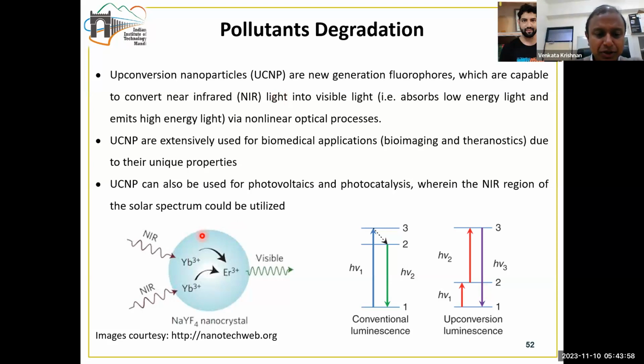When we look at this upconversion nanoparticle, it basically consists of sodium yttrium fluoride as a lattice. It's a nanocrystal type of lattice, and this lattice is doped with certain lanthanide cations such as ytterbium and erbium. One of these lanthanide cations acts as the sensitizer, and the other one plays an active role as the activator. And by tuning the identity of this lanthanide material, we can tune the emission of the light.